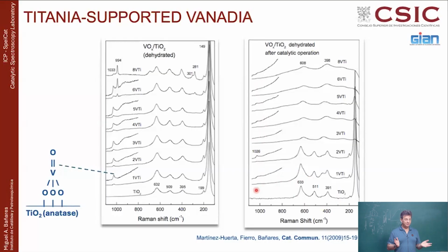Did it fly away? What happened with vanadia? It went down, exactly. It didn't fly away. Other systems you may fly away. With molybdenum, sometimes you get molybdenum oxohydroxides that evaporate and are lost during reaction, but in this case, no. Vanadia doesn't fly away. Whatever happens is that it stays there and sinks into the titania lattice.